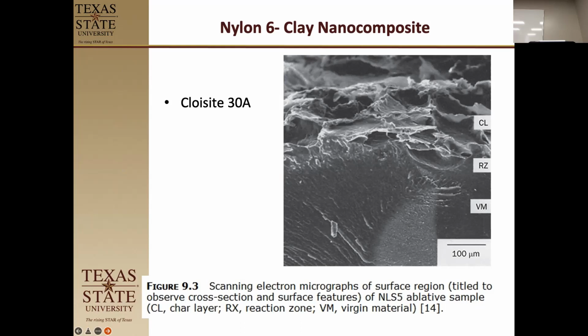So just to understand, the reaction zone, then, that's the actual fuel? This is the part that is decomposing and giving off gases that cause foaming and gases that cause cooling. So it actually helps cool it. It helps draw heat away from that zone. But it's the actual polymer itself going through thermal decomposition. So this is all on the outside? Correct. From where the heat is being delivered this way, you first have your char layer, your reaction zone, and then your virgin material. You're looking down through the thing as it's being burned.